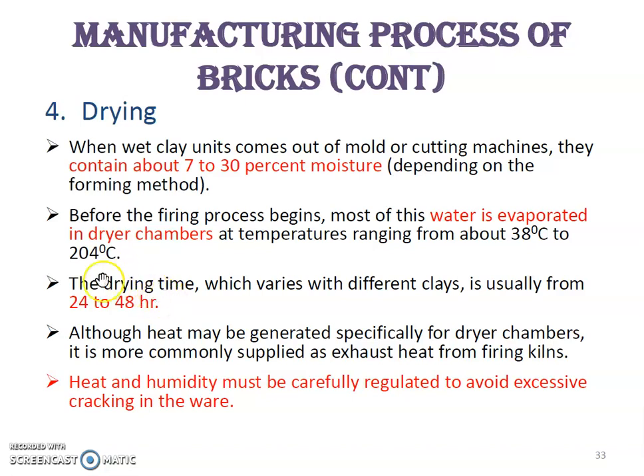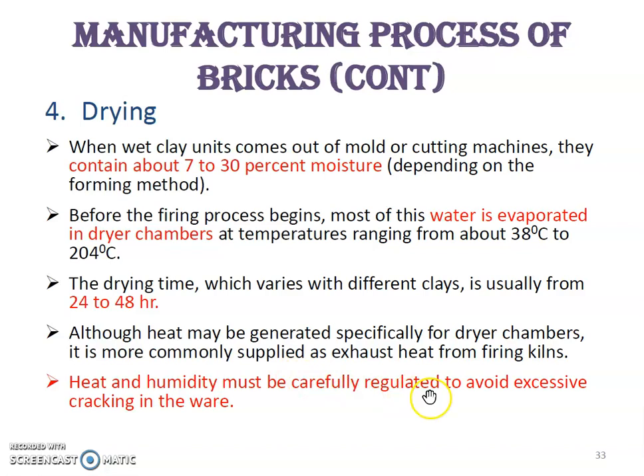The drying time is about 1 to 2 days, varying with different clays. Although heat may be generated specifically for the drying chamber, it is more commonly supplied as exhaust heat from the firing kiln. Heat and humidity must be carefully regulated to avoid excessive cracking.